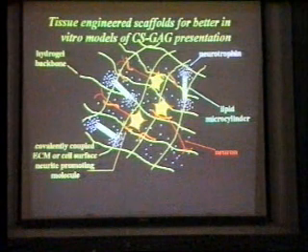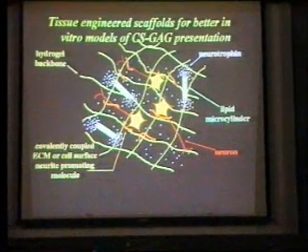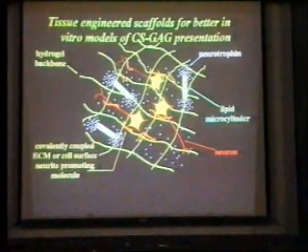So the question then is, are the things that are showing up in excess amounts, like the 6 or the 4,6 or any of these, any more inhibitory than the others? To test that, we used our tissue engineering strategy. Normally in the PNS, we were using these kinds of gels that I showed you earlier in the middle of the bridge to permit growth. Instead of doing that, we coupled the GAGs to the backbone of these gels.